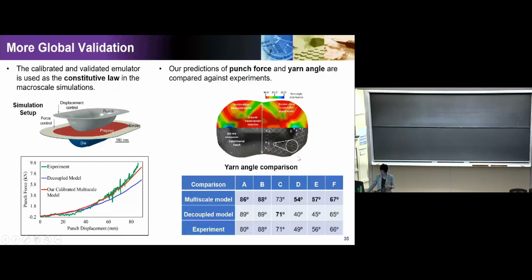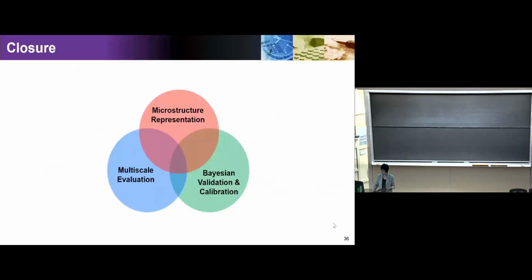And this also has some more detail here, which shows the angle prediction at different locations. That's the output of our model. You can see that the decoupled model is what's in the literature, the multiscale model is from our prediction, and the experiments are the true data. Okay, so you can see that our prediction gets much closer to the true data compared to the decoupled model for the angle prediction. So that's just an example to show how we do multiscale modeling.